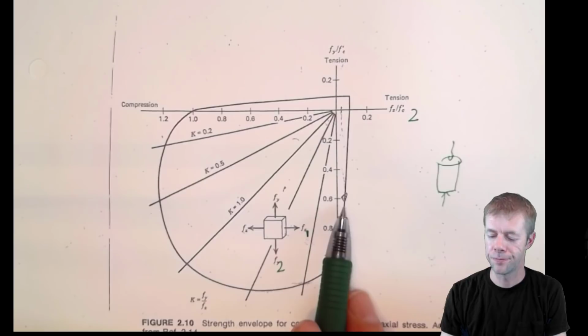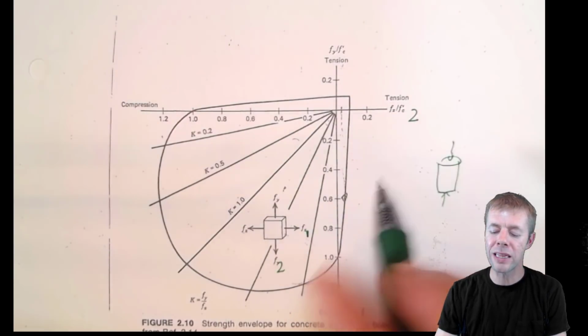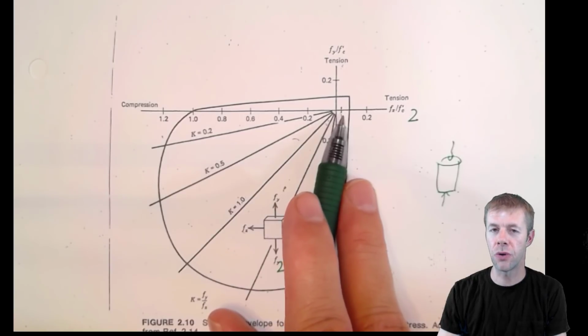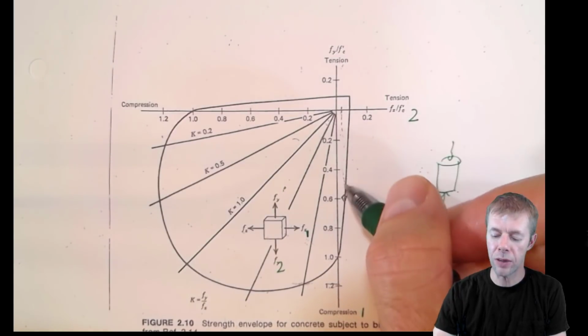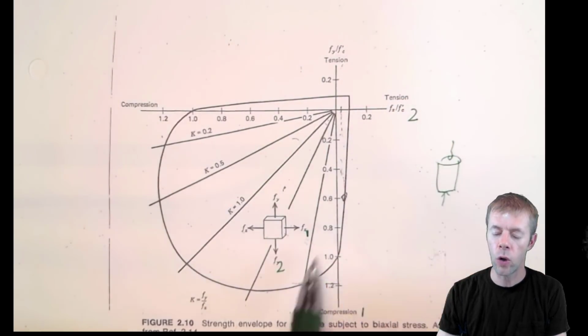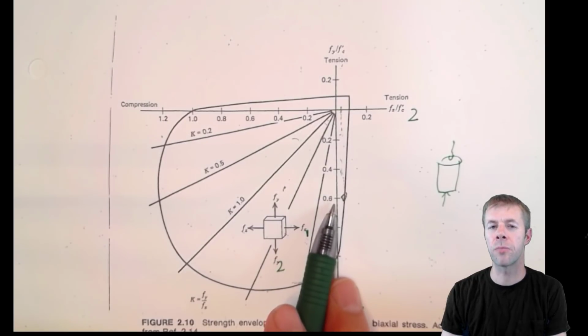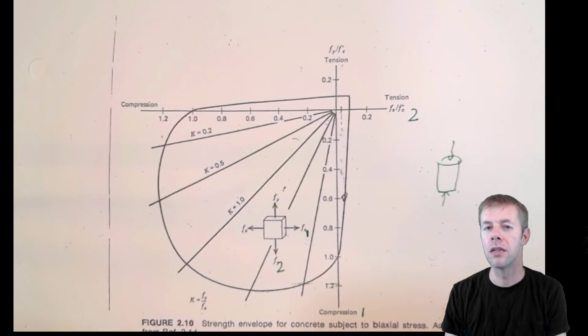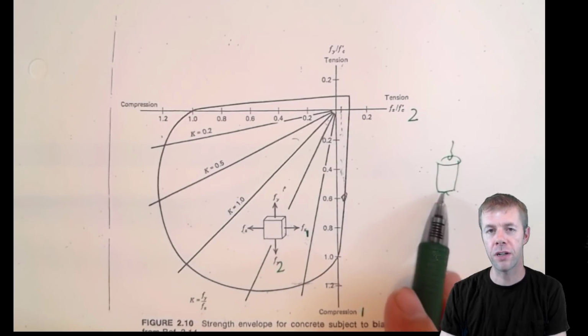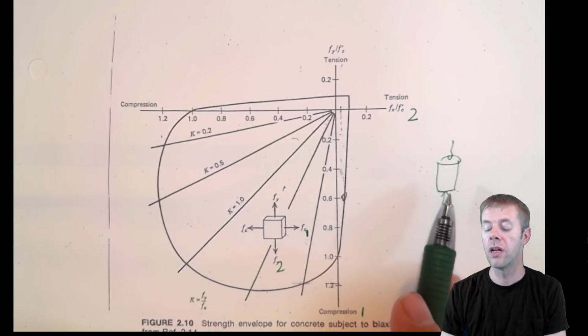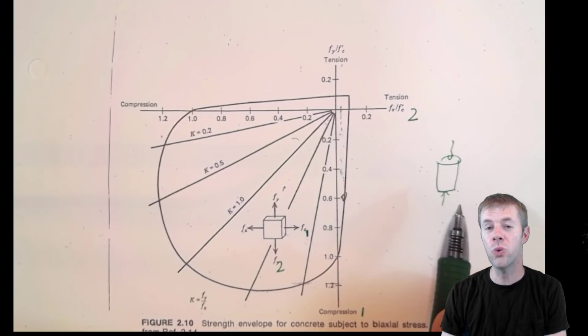But let's look at the bad news. If I even pull a little bit, let's say half the tensile strength, about 0.05 of the compression strength in one direction, my strength drops greatly. If I go down this line here, I'd only be able to take 0.6 of my compressive strength before it breaks. Isn't that crazy? The whole takeaway from this plot is that in real life, our structures are loaded in way different ways than these perfect, ideal cylinders. However, these cylinders or specimens do give us insight into how these much larger structures are going to perform.